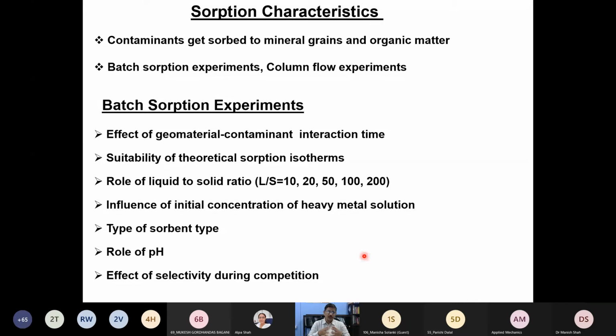Then what you do is you try to represent that a particular amount of contaminant has been transferred from the liquid state to the solid state, or the solid state to the liquid state, whatever may be the case, and then you represent it by using theoretical sorption isotherms. This will really give you the sorption affinity of a contaminant in terms of the retardation coefficient or in terms of the sorption or partition coefficient. So these parameters are going to vary depending on the concentration of the contaminant, sometimes the sorbent type, pH value, temperature. Of course, the moment you call it an isotherm it is at constant temperature, and if it is a soil, the liquid-solid ratio is also going to change.